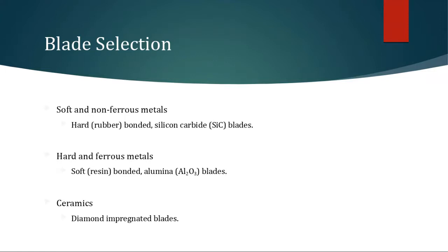So going into soft, and the kind of the theory behind it is when you're cutting a soft material, okay, like aluminum, you're going to want to use that rubber bonded silicon carbide blade. And the purpose of the rubber bond is to hold the particles of silicon carbide in place. Since it's a soft material, you can use this blade over and over and over again. Okay. And the only thing you have to worry about in some instances is not to use a blade that you used for aluminum and then go and try to cut steel or copper with it.